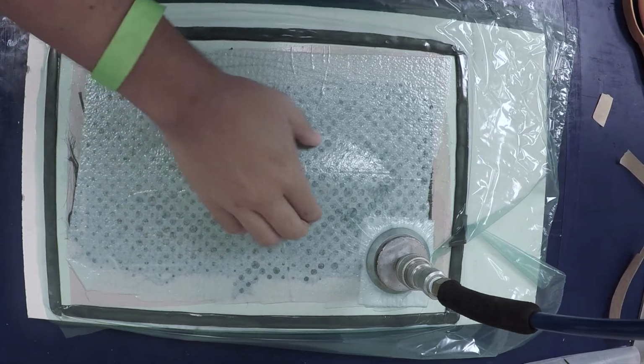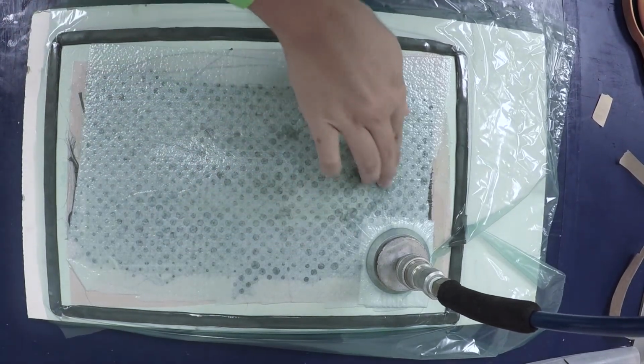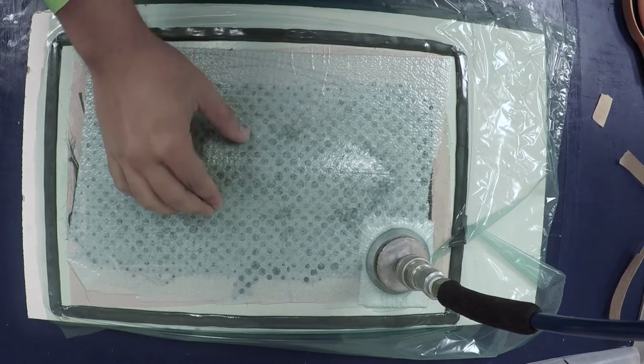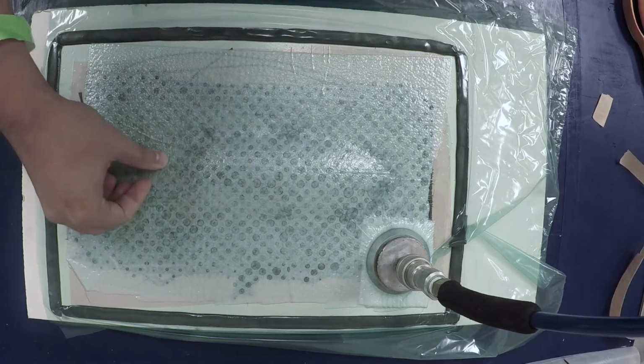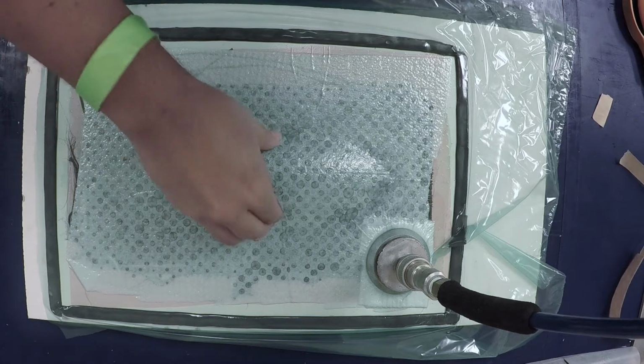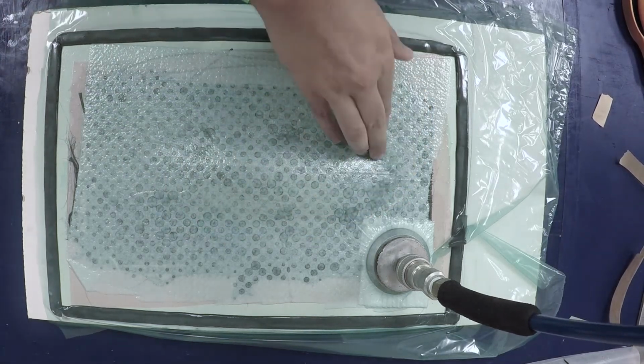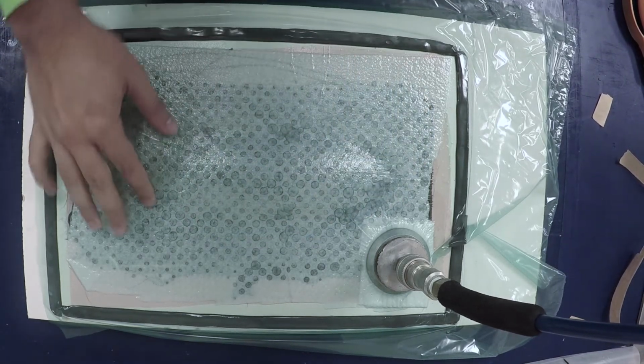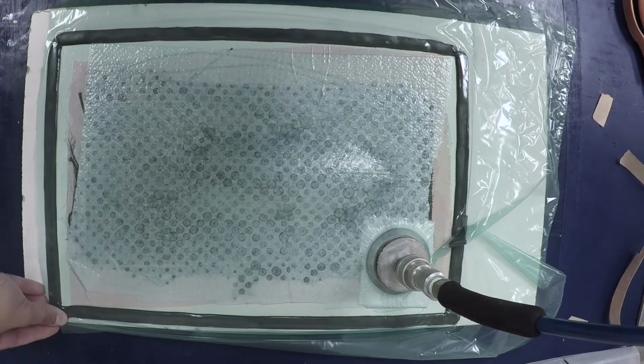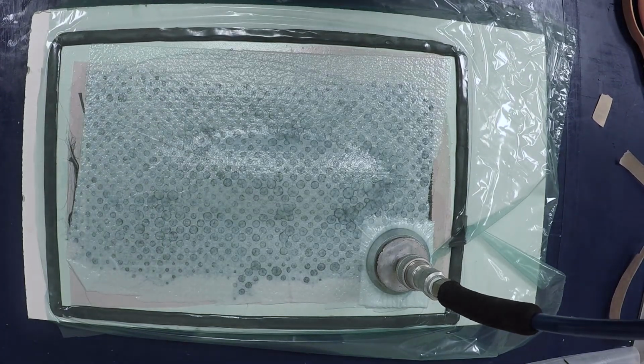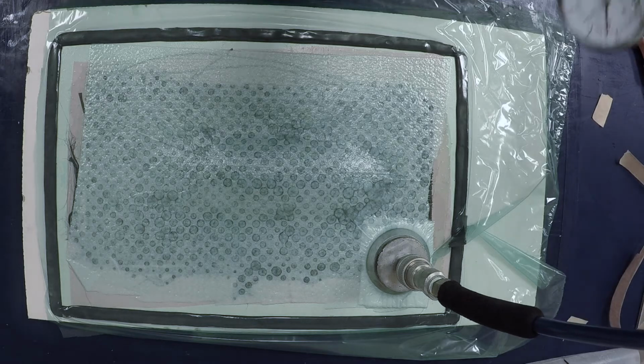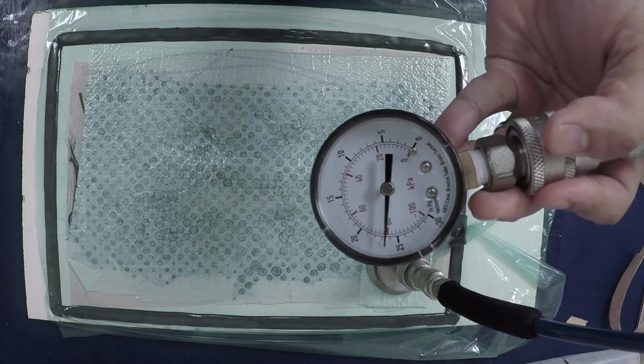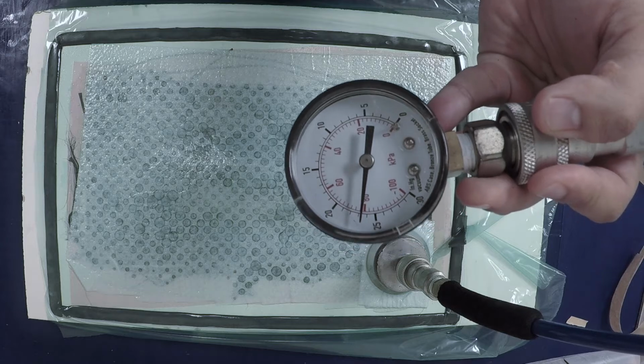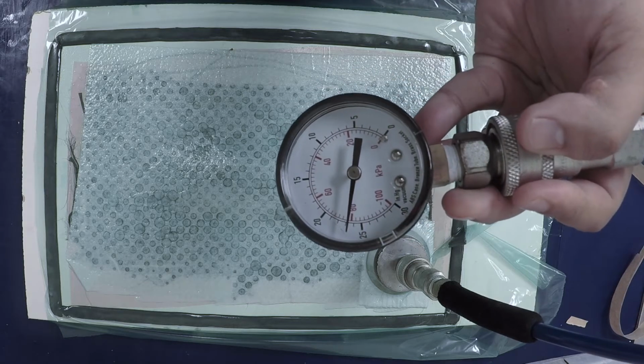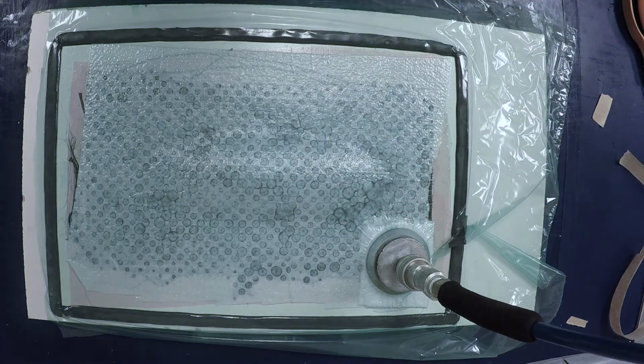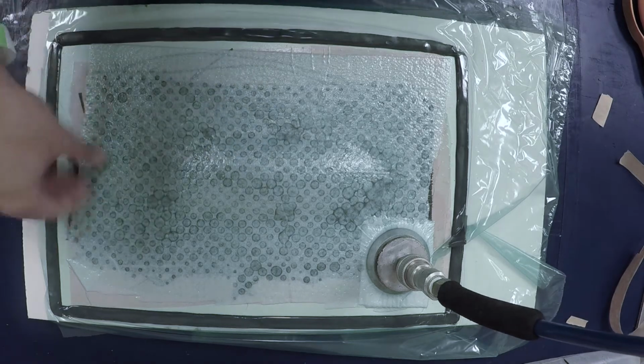Be sure to feel around your mold to make sure that the vacuum bag is tightly wrapped around the mold and that no bridging or any form of gap is formed in between the mold and the fabrics. Lastly, you can check your seal by listening for any leaks. If no leaks are audible, you can double check your vacuum by using a vacuum gauge connected to your system. In our case, our vacuum gauge is showing 24 inches of mercury, which is the correct reference value for our system. After double checking all aspects of our procedure, we can leave our part to complete its curing process.